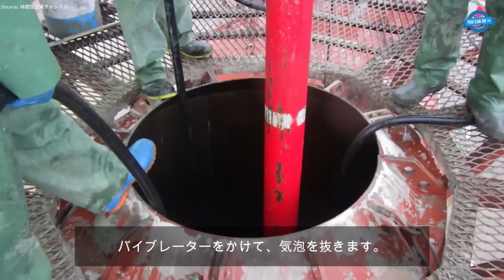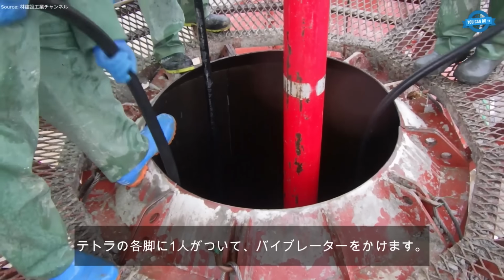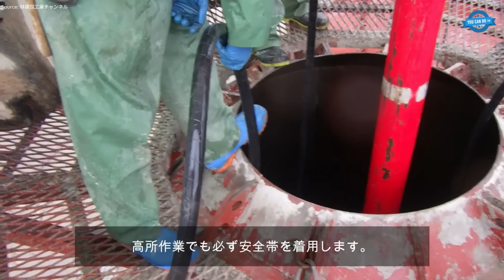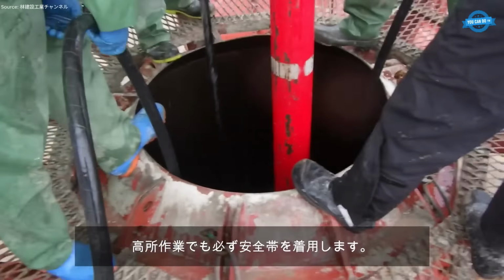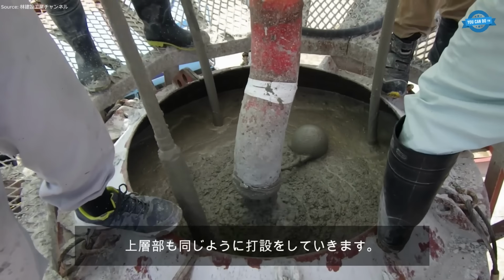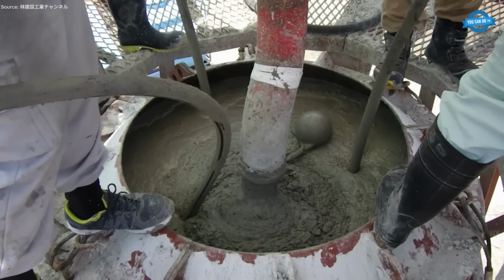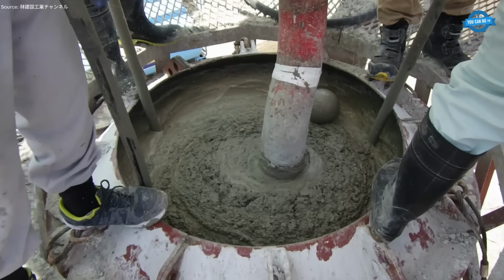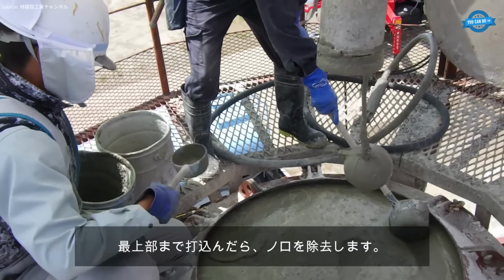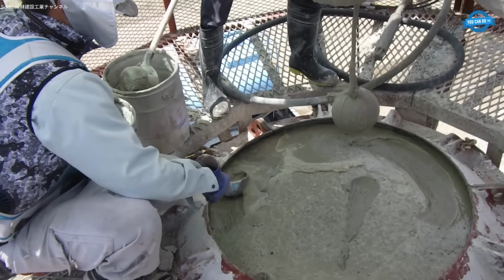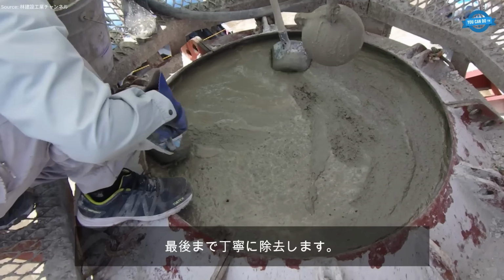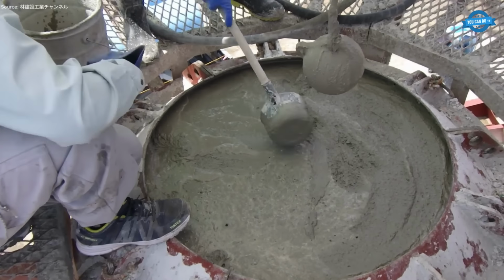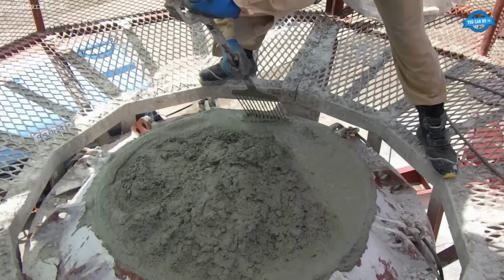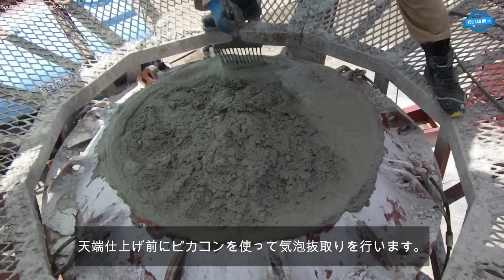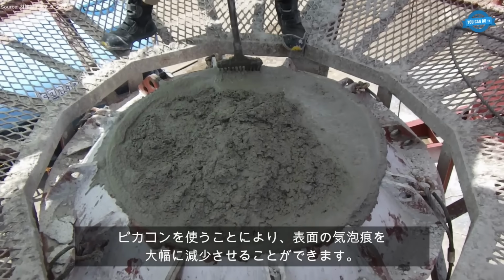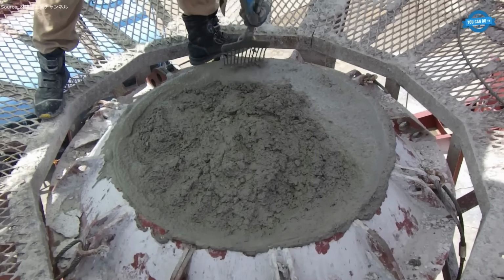Each layer is compacted using vibrators, removing entrapped air and ensuring density, with operators stationed at each leg of the tetrapod. Safety harnesses are mandatory during these elevated operations. As the upper layers are poured, vibrators continue to remove air bubbles. Near completion, nozzle residues are carefully removed, and finishing is performed with a Picacon device, reducing surface voids. A curing compound is then sprayed over the exposed surface, followed by temporary covers to prevent rapid moisture loss.